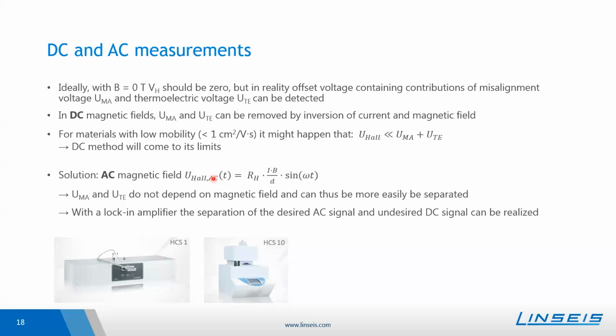The advantage of using this AC magnetic field is that these offset voltages, the misalignment voltage and the thermoelectric voltage, do not depend on the magnetic field. So by having the sinus on the magnetic field, you will not have the sinus on both of those two contributions. And by that, these still remain as a DC signal and thus can be more easily separated just by using a lock-in amplifier. With the lock-in amplifier, you can then separate the AC signal, which belongs to this Hall voltage, from the undesired DC signal of these offset voltages. So in samples with a low mobility, the usage of the AC magnetic field can be advantageous, and in our case, this can be realized with the Hall characterization system 10.